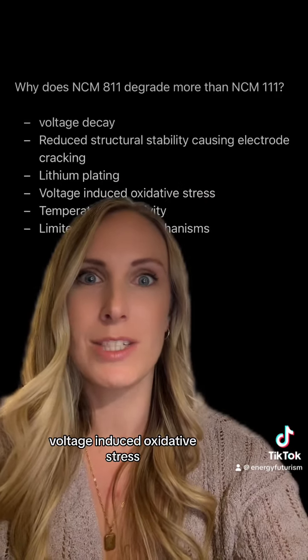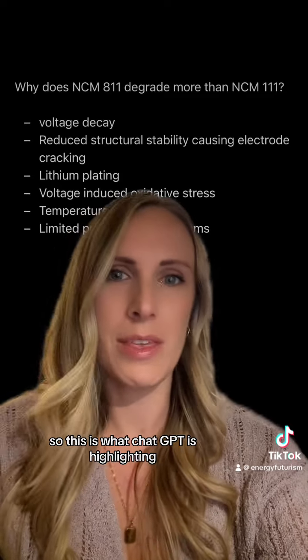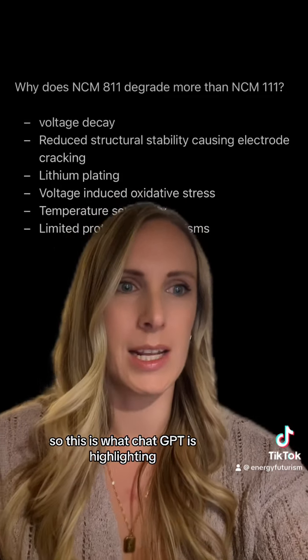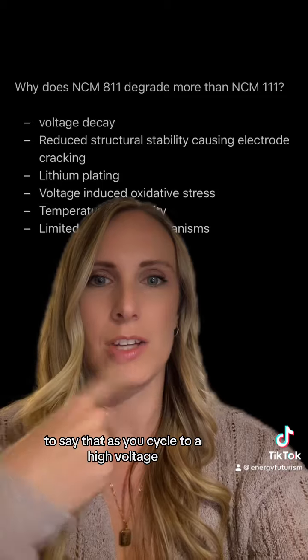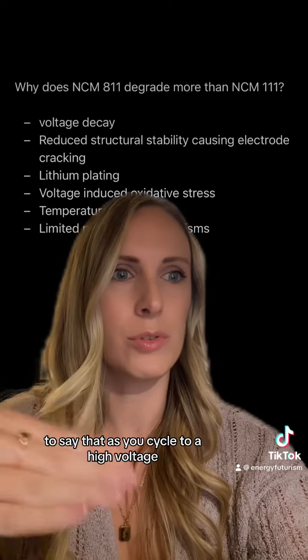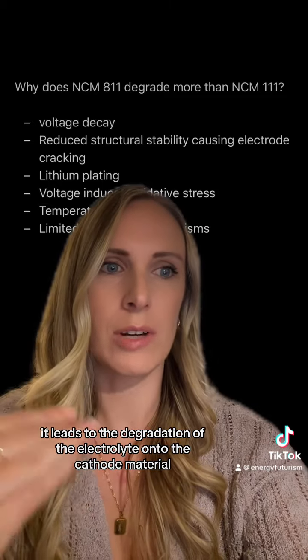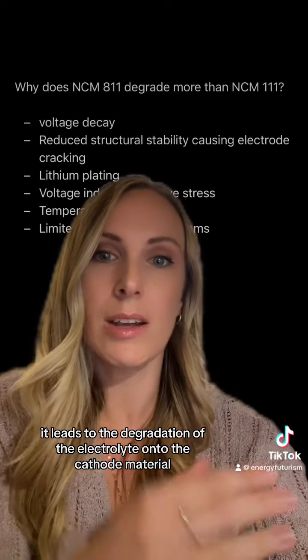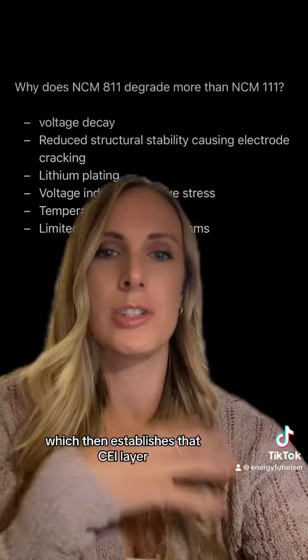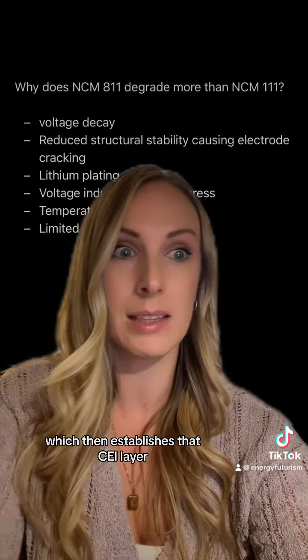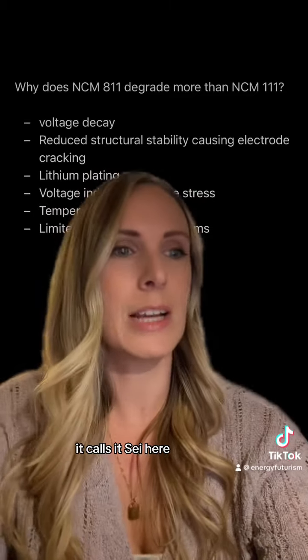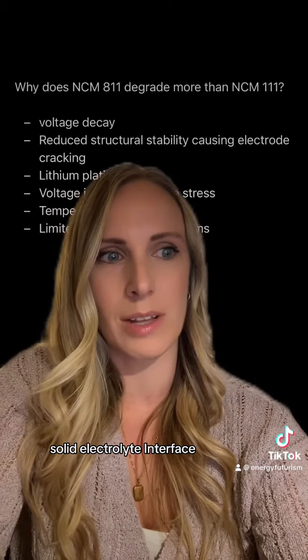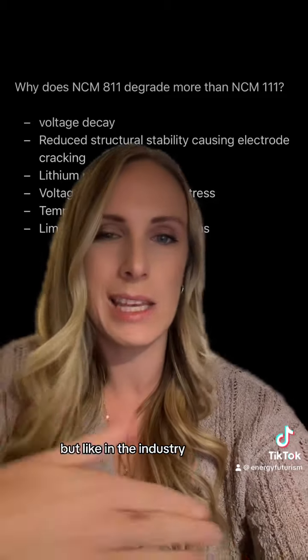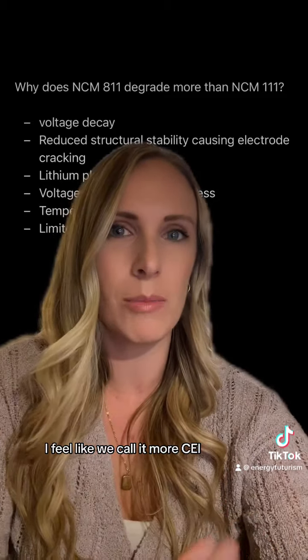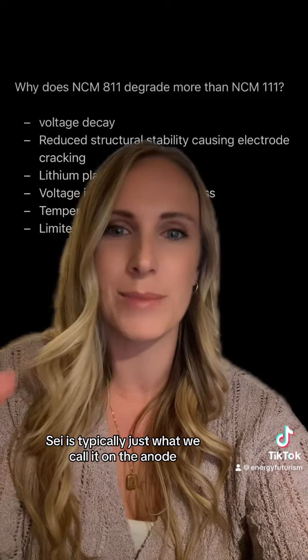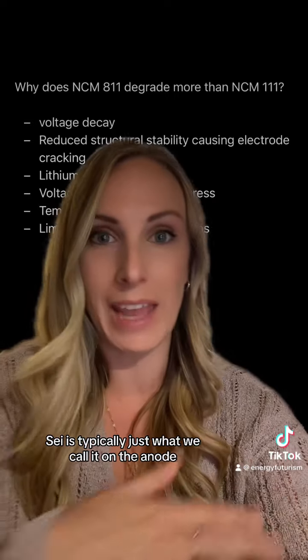Voltage-induced oxidative stress. So this is what ChatGPT is highlighting: as you cycle to a high voltage, it leads to the degradation of the electrolyte onto the cathode material, which then establishes that CEI layer. But it calls it SEI here, solid electrolyte interphase, which is true, but in the industry, I feel like we call it more CEI. SEI is typically just what we call it on the anode.